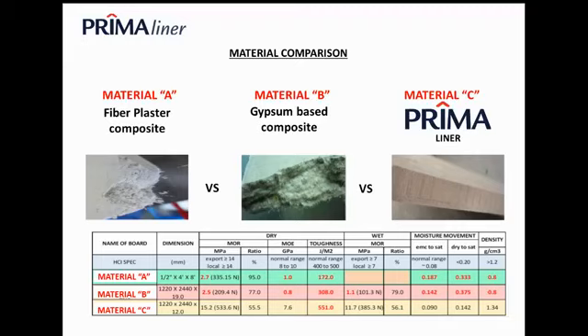Well, of course, any material when it's dry is strong, but let's look at the material when it gets wet. So we also did MOR tests in wet condition. As you can see, for material B the MPa is 1.1, whereas material C, Prima Liner, is still a lot higher, which is 11.7. Definitely all materials will drop in terms of performance when they get wet. But it's still within the tolerance and it's still better compared to the other two materials when they are dry. So there you can see.